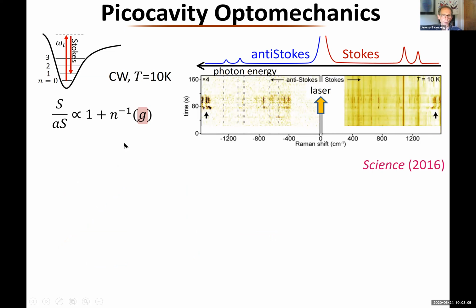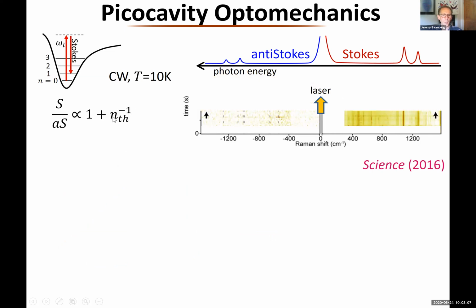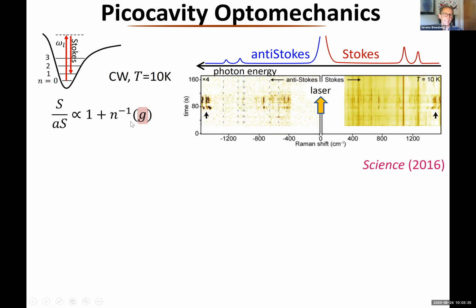The reason it's not thermal, so we normally say it's thermal because we're in an equilibrium system. We say that the population of these states is thermalized. But what's happening here is I'm driving this so fast, the G is so large, that I excite many of these, and it's not thermal, I excite them before they can relax. So what I get is the instantaneous population in that state, which is dependent on G. I see. So this is a non-thermal population. This is a non-thermal population. An effective temperature. Okay, thank you. Yeah, it's an effective temperature of thousands.